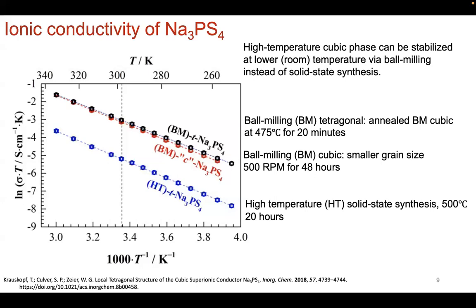Yes, although the ball mill tetragonal has been annealed from the ball mill cubic, whereas the high temperature solid state does not have that. So it's starting already from the cubic. So when you anneal, you have a different average structure, but the same local structure. At least that's what X-ray PDF seems to indicate.